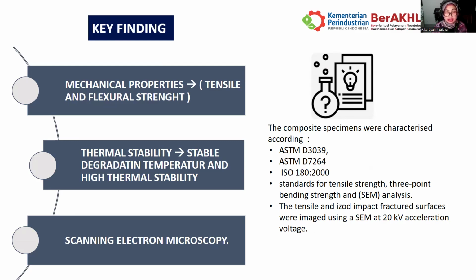From this journal and also from the research, the scientists found three key findings. First, the mechanical properties, including the tensile and flexural strength. The tensile and flexural strength are improved in value by increasing the fiber volume fraction, and at the end it reaches optimal performance for specific fiber contents. The mechanical properties are also comparable to wood, indicating suitability for structural applications.